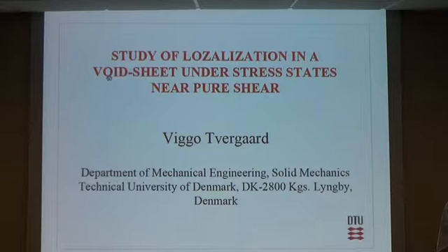The mathematics of these equations, finite strain and so on, I don't need to talk about, because they are as I explained. So here's a mesh used for this situation. Due to the boundary conditions, we must expect that in the outer region of this unit cell, we will have stress and strain states that become exactly the same as those at infinity. Also, we only have this one row of voids. This is plane strain, by the way, a plane strain approximation. Because we only have one row of voids, the void volume fraction in the whole solid is 0. There is only one row of voids in an infinite solid.